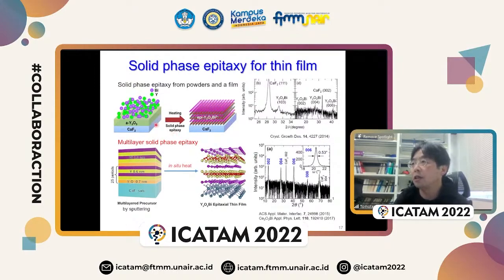This is the first generation solid phase epitaxy. At first we feed bismuth and yttrium powder, and the bismuth powder and yttrium powder react with each other. After that, secondly we feed this bismuth yttrium powder and amorphous Y2O3 on a calcium fluoride substrate. This is a single crystal substrate. And finally, we obtain a Y2O2Bi epitaxial thin film. This is the XRD pattern of this thin film, and the XRD peak is very small. So this means the crystallinity is not sufficient.